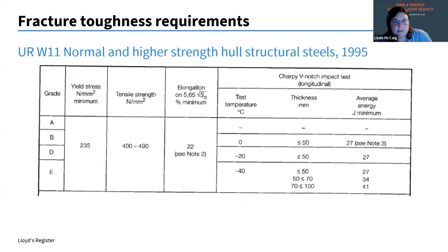Move on to 1995. We've now got a range of thicknesses. So we're starting to look at the thickness of the steel as being quite important, as well as the average energy in the test and the test temperature. But again, still nothing for grade A.